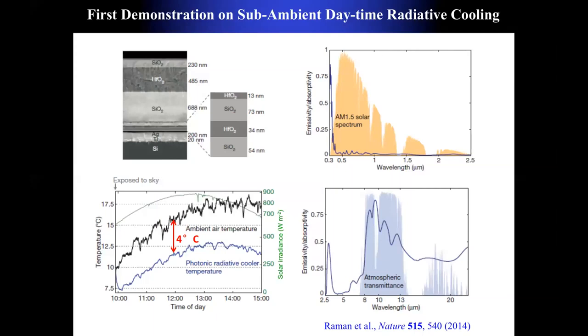Now, the challenge is that these materials are made of multilayer oxides. And it's reasonably delicate engineering, because you see layers of 13 nanometer, 73 nanometer, and 34 nanometer. It's an engineered structure. It makes it difficult to produce at large scale, and it could be costly.